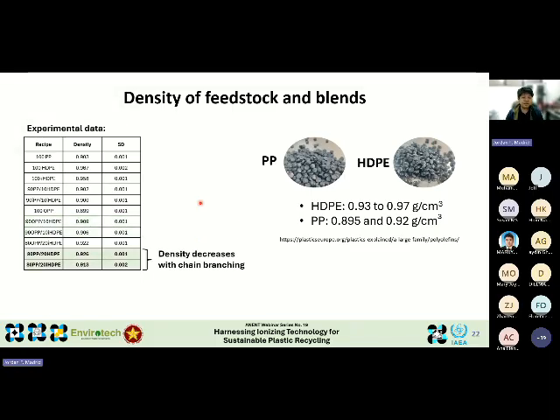Finally, when we look at a different formulation—earlier I showed results for 90:10—this time we also performed the test with an 80:20 polypropylene-HDPE blend, which I will explain in detail later. We still saw the same effect: the use of irradiated HDPE contributed to a decrease in density. Of course, density measurements give us a good initial indication of chain branching, but we are also exploring other techniques to further analyze this behavior in HDPE, and perhaps in the future I will share those results with you.